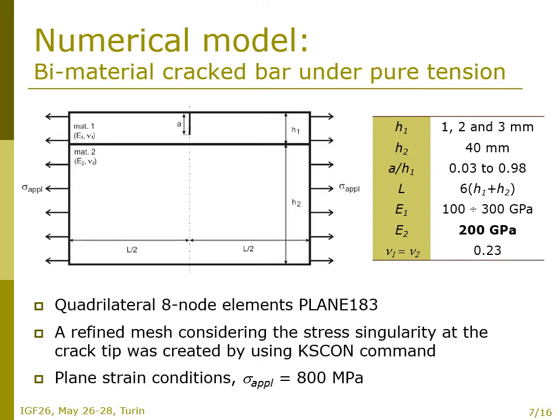A numerical model was created as a simplified bimaterial cracked bar under pure tension in the first step of the research. Here you can see the schema with the particular dimensions in the figure and in the table. Whereas the elastic modulus of the substrate was kept constant at 200 gigapascals, the elastic modulus of the surface layer was varied from 100 to 300 gigapascals. Also, the influence of the thickness of the layer was investigated, and the values of 1, 2, and 3 millimeters were considered. The crack was modeled from very short to very long in the surface layer.